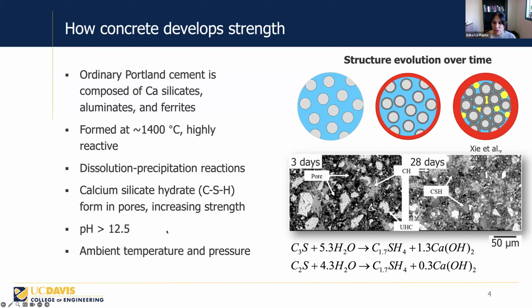And really the remarkable thing about this material is that all of this happens at ambient temperature and pressure. These equations here show the cement notation for the reaction of C3S. This is just a cement notation that represents 3 units of calcium oxide and 1 unit of silicon dioxide reacting with water to form CSH, and then the other hydration product is what we call calcium hydroxide or Portlandite.